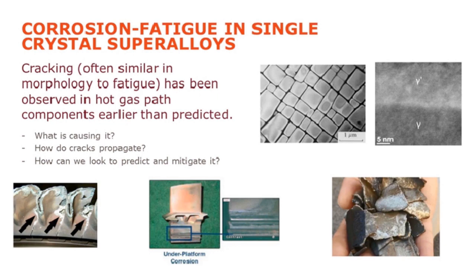So they're both face-centered cubic, and the gamma prime is an L12 ordered face-centered cubic. Just next to that, the really high mag 5 nanometer image is showing you the interface between that gamma and the gamma prime. So really this is what makes these materials a bit special. Whilst you've got two phases, because the unit cell size is so comparable, we don't really see a phase boundary. You can see the lattice coherence is really very good